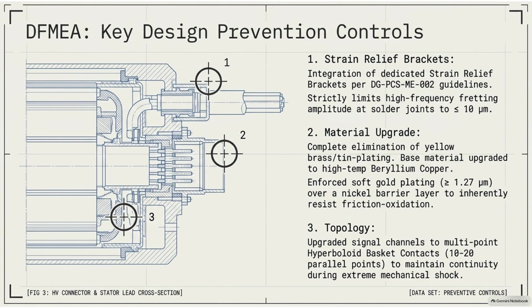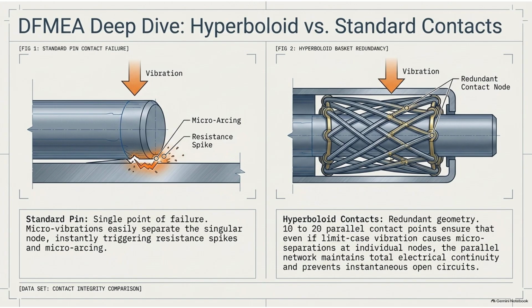Because the gold doesn't oxidize and because it lubricates the friction point, there is zero insulating buildup. The electrical resistance remains flawlessly flat forever. It completely prevents those black spots of friction oxidation from ever taking root. By eliminating the microscopic resistance spike, they completely neutralize the conditions required for microarcing. They use material science to mathematically forbid the lightning strike. That is an incredible application of chemistry to solve a mechanical problem. But the physical shape of the connection changes too, doesn't it? The DFMEA specifies a shift away from standard flat pin connectors to something called a hyperboloid basket topology.